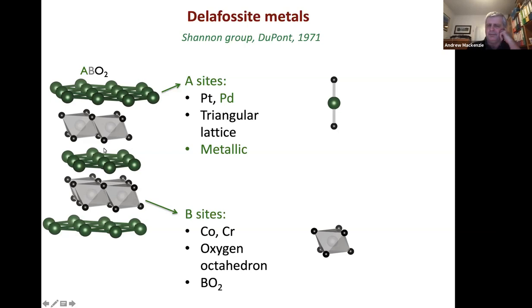So if we look a little bit deeper, on the A site, you have your platinum or palladium, and chemically, something which is emphasized in the chemistry papers is that you have a very unusual bond, a linear metal oxygen bond. And that allows palladium and platinum to exist in a valence which is extremely rare for those elements, the 1+ valence. And in terms of electron counting, this would be one unpaired electron sitting there in the d3z²−r² orbital of the 4d orbitals.